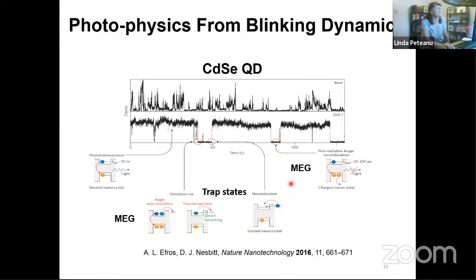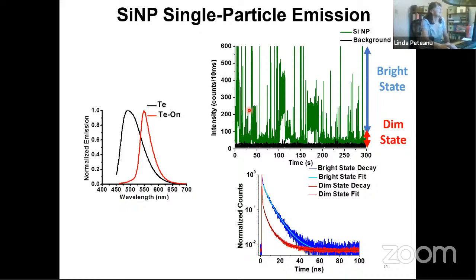Basically, these will give you a charged crystal, and once you can recapture the electron, you can get the system to re-radiate. So basically, the dark systems are telling you about MEG type processes as well as the presence of traps. So we see a very similar type of phenomenon when we look at the silicon nanoparticles. So these are the ones that are 90% quantum yield emitting in the yellow, with this particular ligand combination. So you see these bright bursts of emission, but you also see this kind of low-lying emission here. And so the bright bursts we're going to call the bright states, very imaginatively. And the dim emission here, we also see sort of on all the time. And then the black line here essentially shows what the dark noise of our detector is.